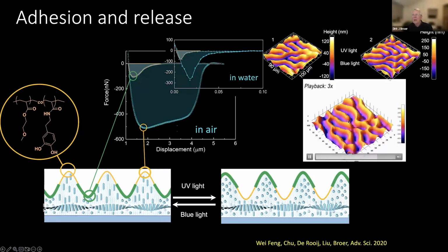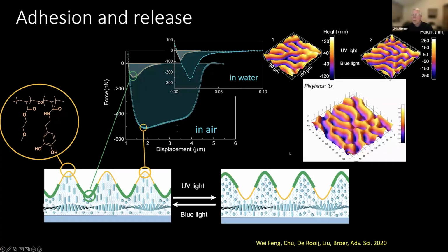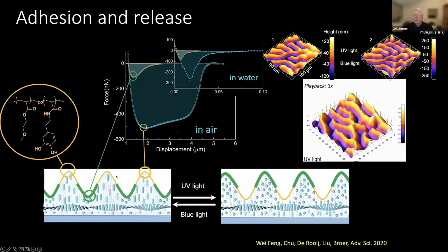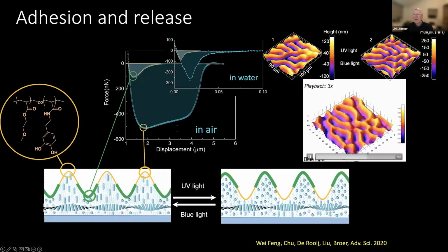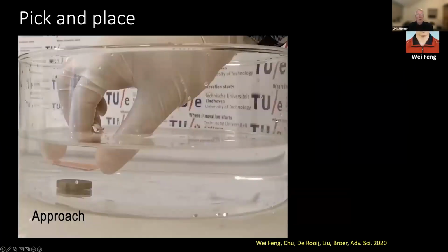And basically what you can see here is actually the dynamics of our surface inversion. So now, let me start again. So now the adhesive state is at the top, and as soon as we expose it to UV light, it is inverted, and now the non-adhesive parts are at the top. Yeah, and again, this is played back at three times the speed, but it is still within a reasonable time frame.